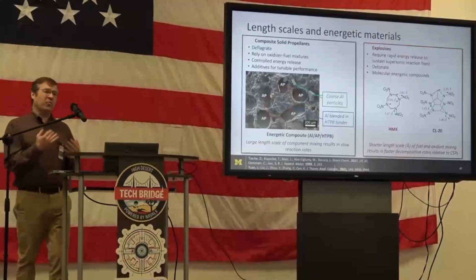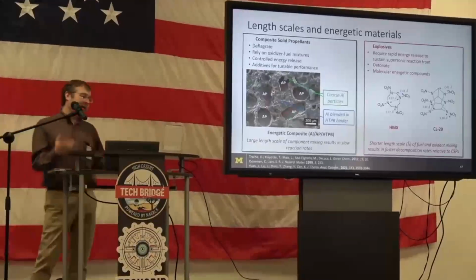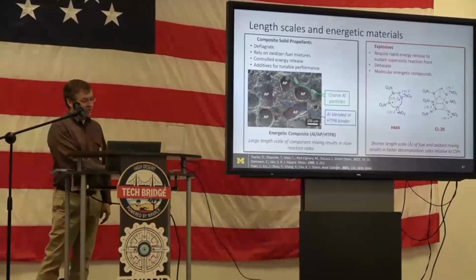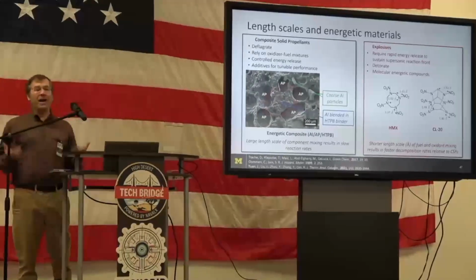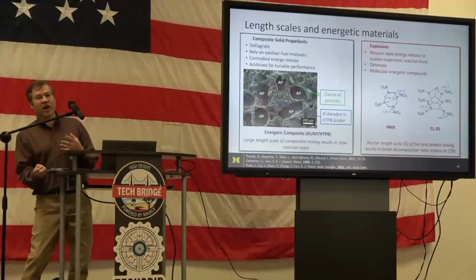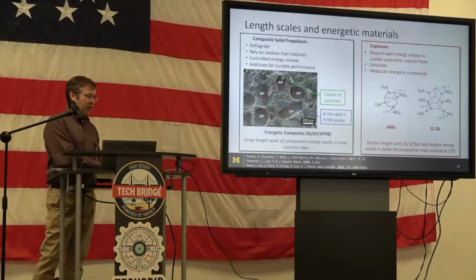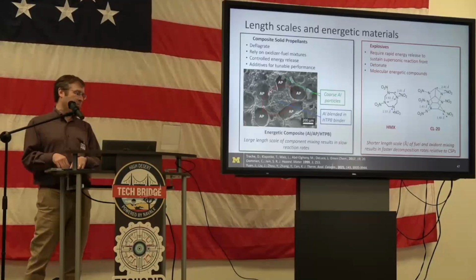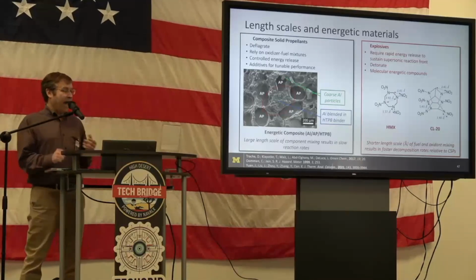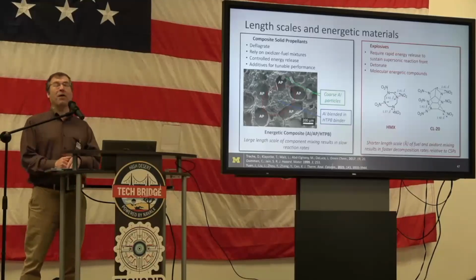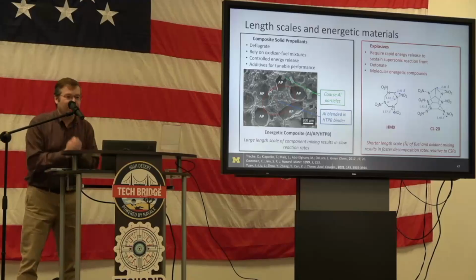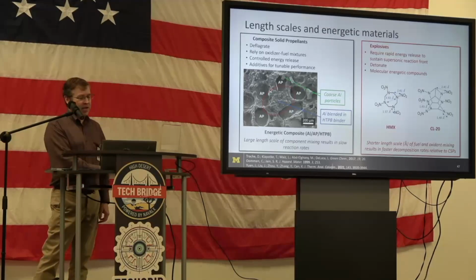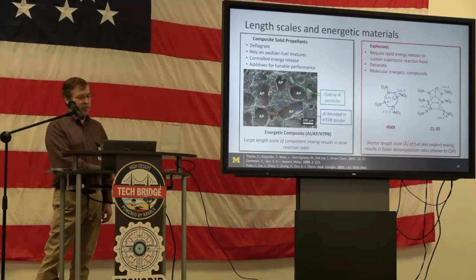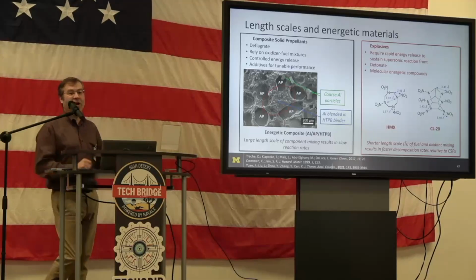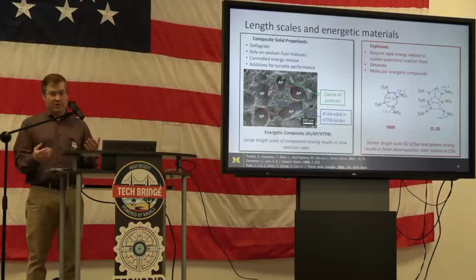And I want to talk a bit, just a speck, about length scales. When I think about length scales in energetic materials, you think about composite solid propellants, where you have microns, hundreds of microns between oxidizer and fuel in some cases, between your aluminum or your HTPB and your ammonium perchlorate. An explosive, you can think of as a molecularly bound composite, right? And the length scales are very short. We're talking angstroms, which is why you get super fast reaction rates when this nitro goes to oxidize this methylene, whereas when you try to get AP to oxidize the butadiene, it's a much slower reaction.